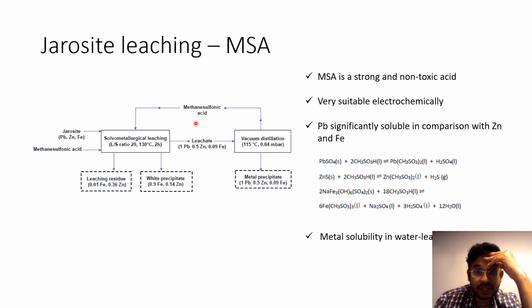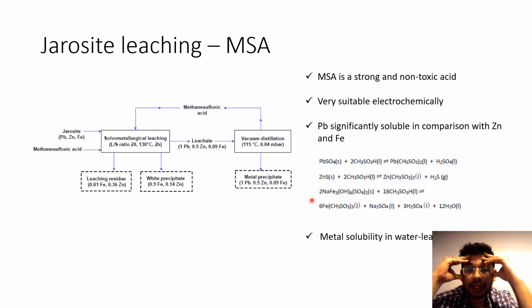So essentially, this is a very interesting process because of all the important attributes of MSA, methane sulfonic acid, but also the fact that you can indeed capture the acid back and then send it through a simple vacuum distillation step. And that is the major advantage of the jarosite leaching through MSA. So they didn't go on with the route with electrochemistry because it could also be that some of it can be selectively deposited. They didn't proceed further. But yeah, it's an ongoing work, and you could see that coming maybe in the next couple of years.